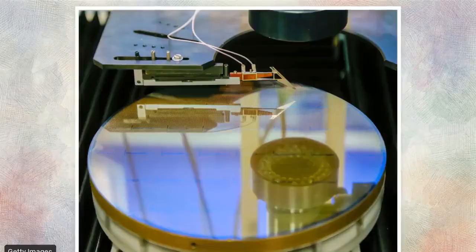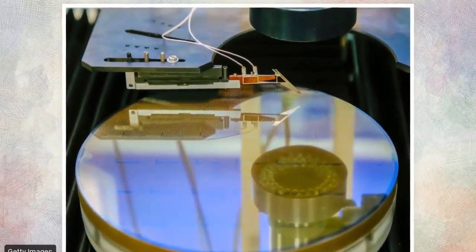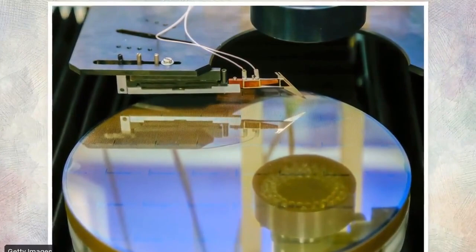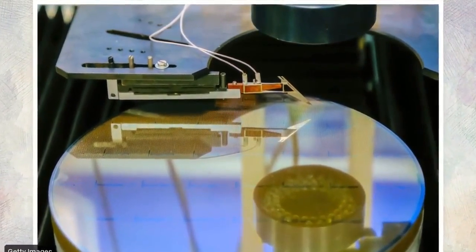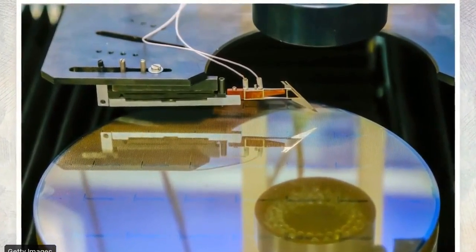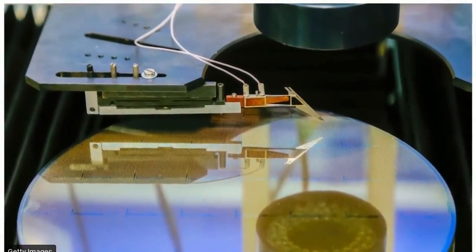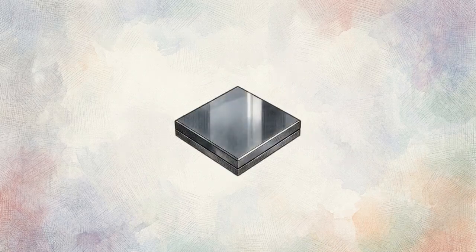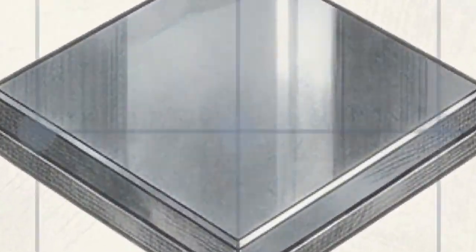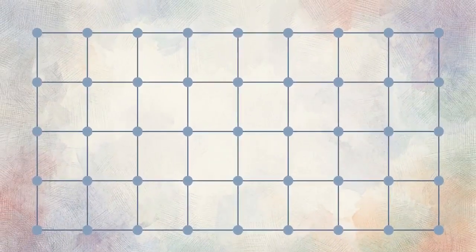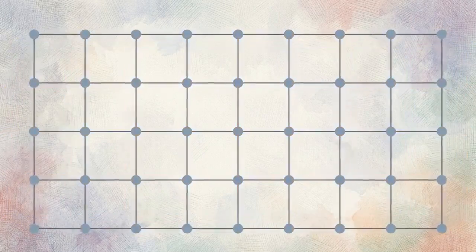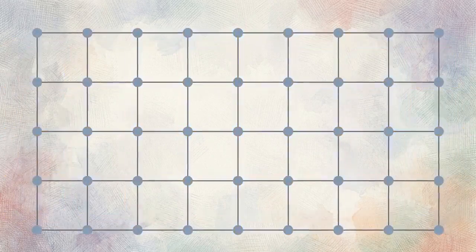Over time, these grain boundaries cause standard metallic watch springs to succumb to fatigue, eventually losing the elasticity necessary for precision. To solve for metal fatigue, Omega integrated silicon, specifically Si-14. This high-purity silicon wafer is the exact same foundation used to print modern computer CPUs. Silicon has different physical properties. It is a single crystal material, forming a flawlessly repeating grid of atoms extending uniformly in all directions. Because this lattice lacks internal grain boundaries to harbor stress, it is far less susceptible to fatigue than metallic alloys, retaining its structural integrity over millions of cycles.